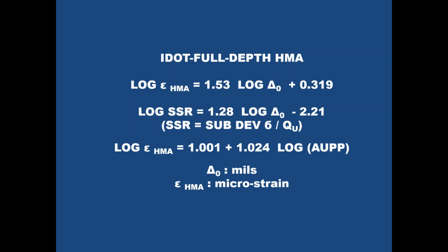We can relate deflection to strain for our full depth sections in Illinois based on that equation. We validated that. The subgrade stress ratio we can predict as a function of delta naught. Log of strain here is a function of AUPP. We didn't use this for many years. We confirmed it hardcore. Minnesota road test has used it ever since. It's a valid relationship and works very well.